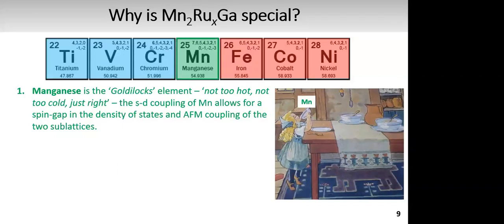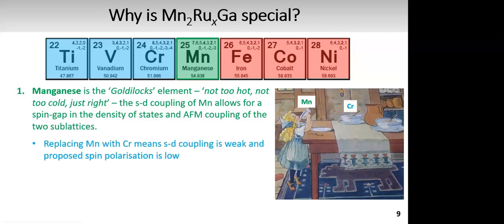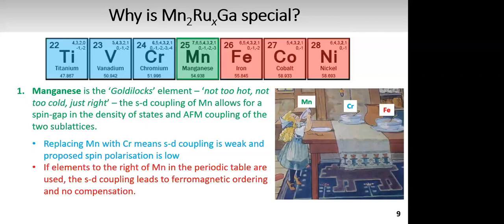Then if we look at the periodic table, if we were to, for example, replace manganese with chromium, it would mean that the sd coupling is weak and the proposed spin polarization would then be low. And also looking at elements to the right of manganese, for example iron, this would lead to the sd coupling being stronger, which would then give rise to ferromagnetic ordering, and we wouldn't have compensation. And one of the conclusions here is that it is possible that most, if not all, zero moment half metals will contain manganese.